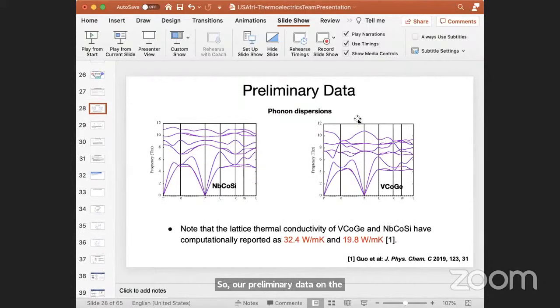So our preliminary data on these two compounds: we tried to look at the dynamic stabilities of these compounds, and we found that the phonon dispersion gives us positive frequencies, which means that the materials are stable. Also, in the previous work in 2019, these materials were predicted to have a very high lattice thermal conductivity.